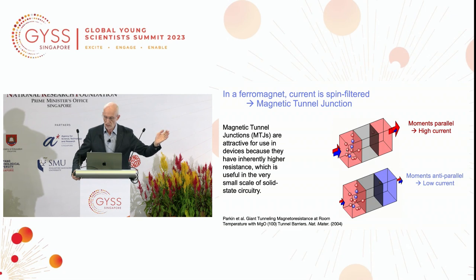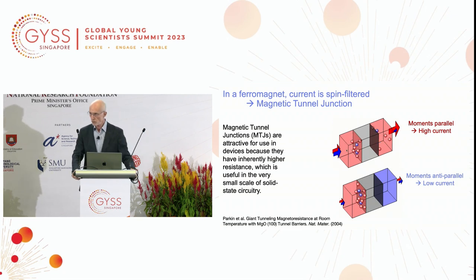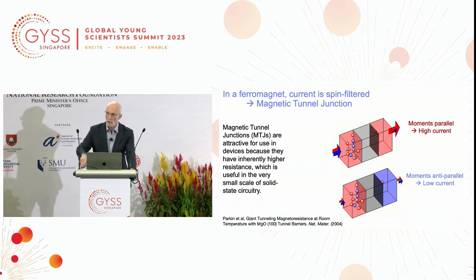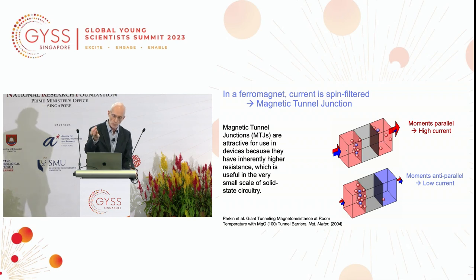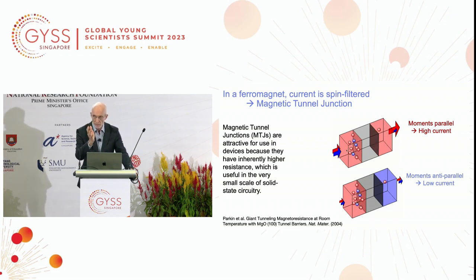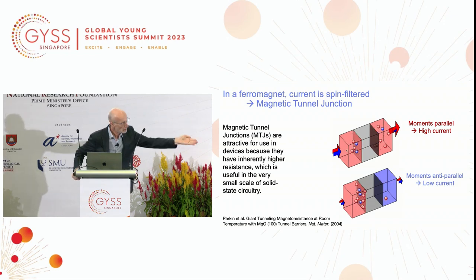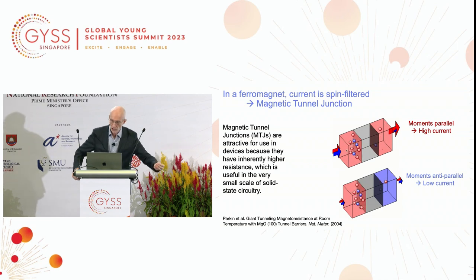So you see again the red and blue layers that correspond to their magnetic moment direction. But now instead of a metallic layer in between, we have this thin gray layer. This is an insulator, no electrons. So the electrons now quantum mechanically tunnel from one metallic electrode through the insulator to the opposing metallic electrode.